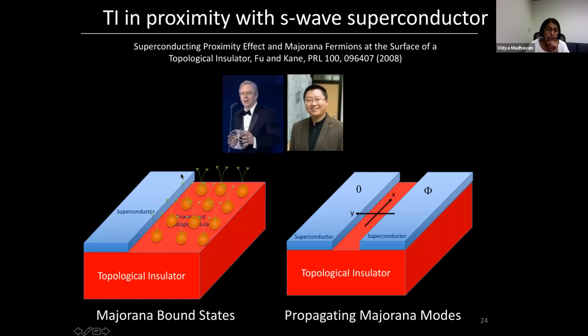You have the superconductor. The topological insulator basically gets rid of spin as a separate degree of freedom. And the reason is that in a topological insulator, I didn't show you this, but like I was saying, there's only one species of spin for a given momentum. And in fact, spin is locked with momentum in a topological insulator. So essentially, once you know the momentum, you know the spin. So that takes care of that.